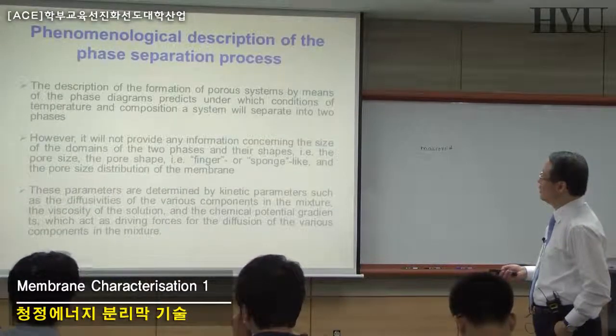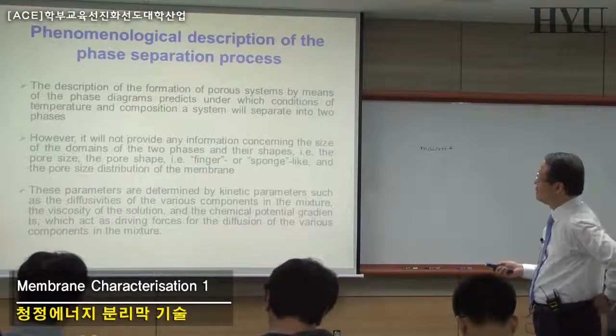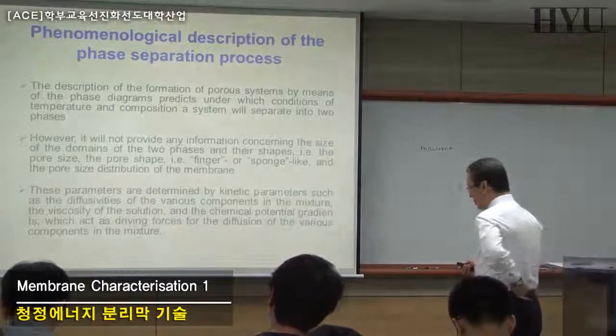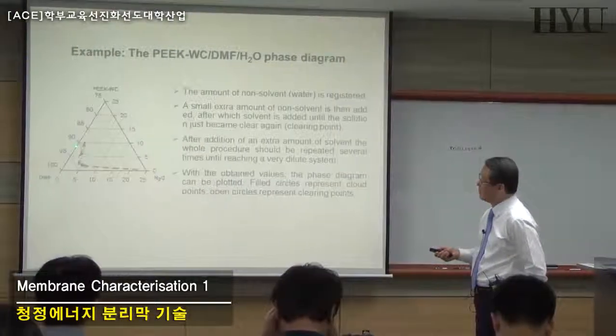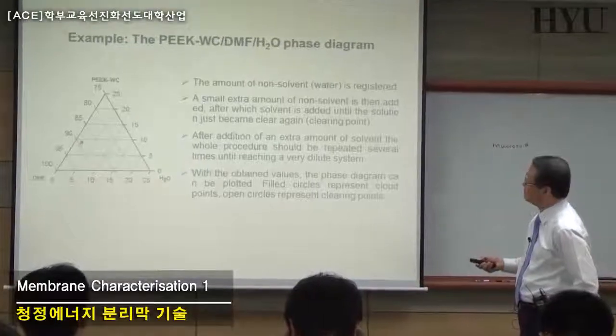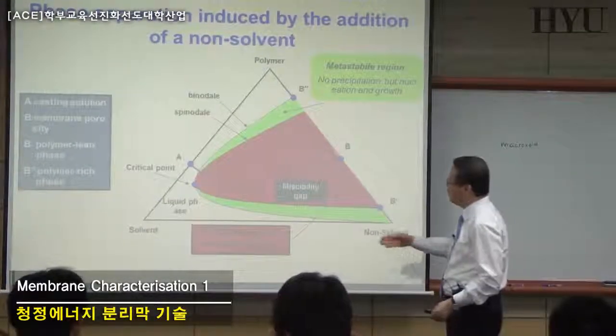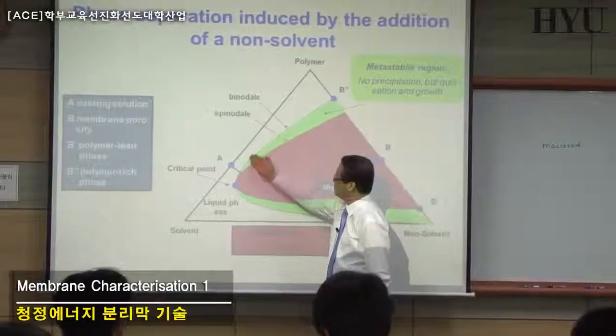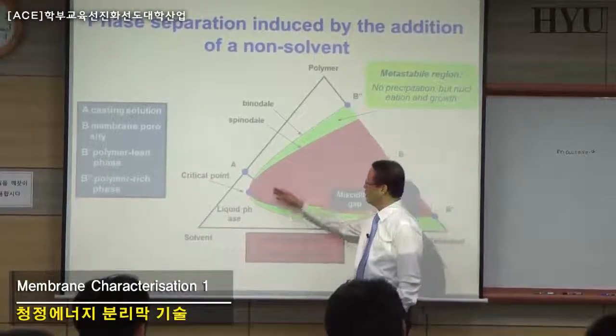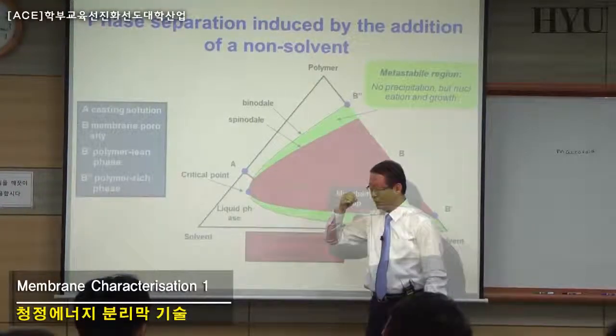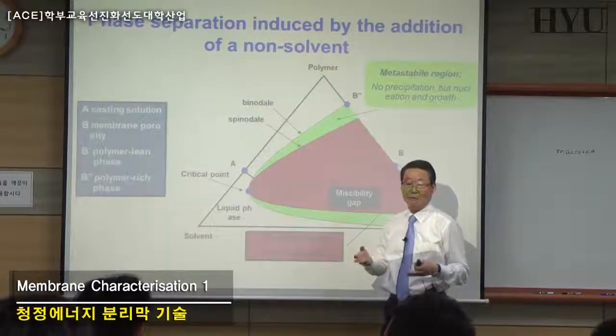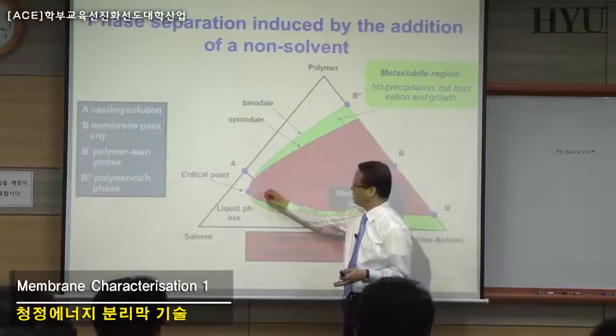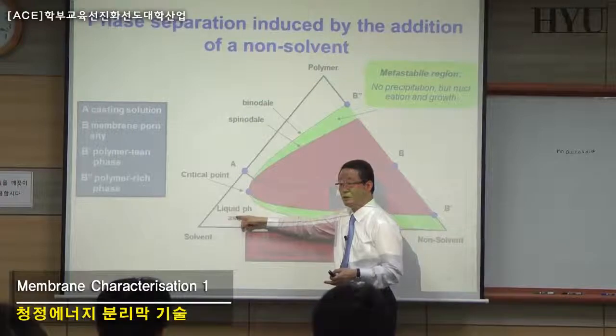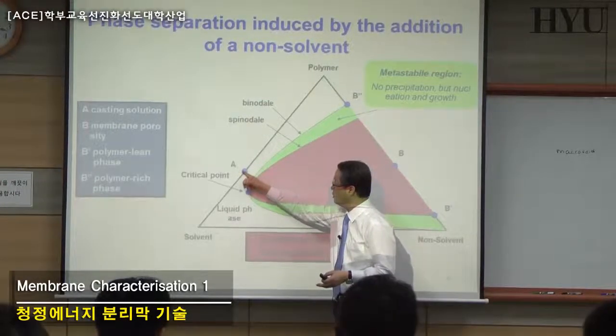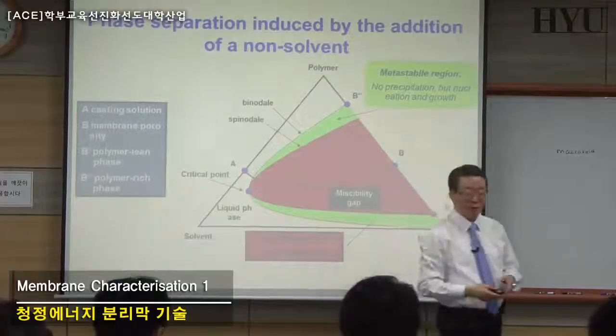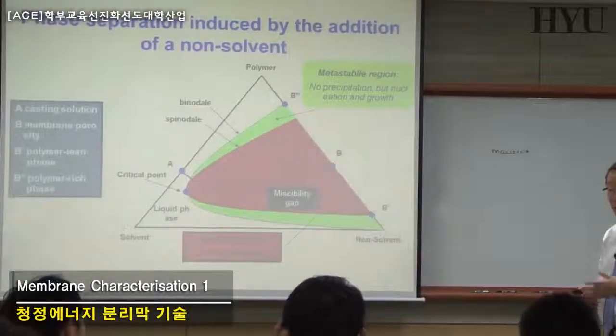After making these binodal curves, if you go back, okay, if you go back, this way you can draw the binodal points. The next thing that you have to think about is where you should start to make your membrane. Whether you start your membrane from this point or here will determine the final morphology of your polymer membranes.